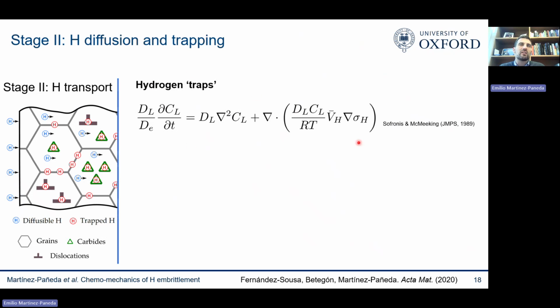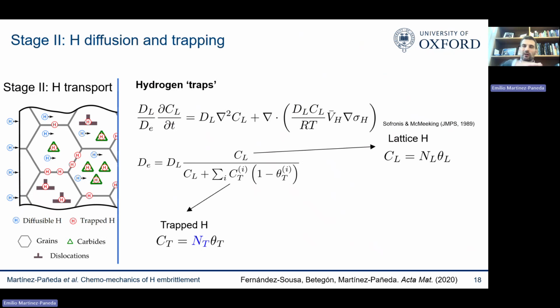You can see here, this is very similar to what we had before. The only difference is that now we have an effective diffusivity that basically characterizes the fact that as the hydrogen encounters those traps, it slows down its lattice diffusivity. So basically, the model relies on two parameters: you now have a lattice hydrogen concentration and a trap hydrogen concentration.